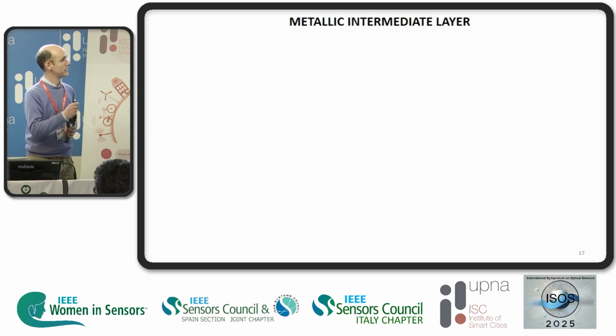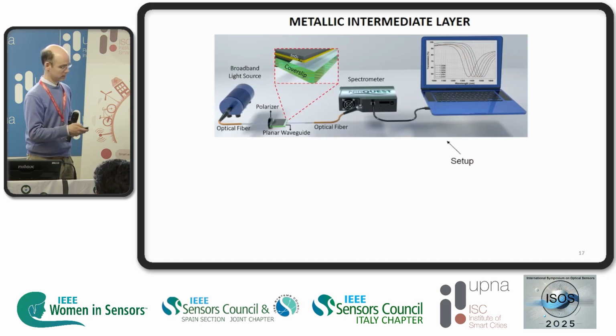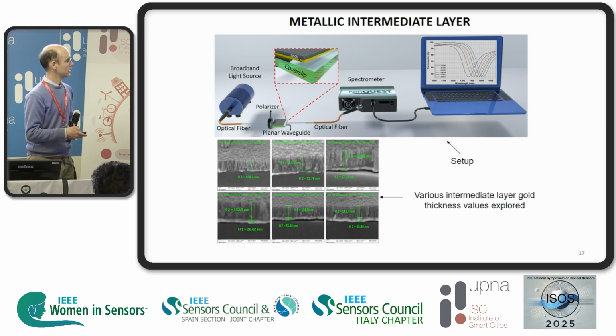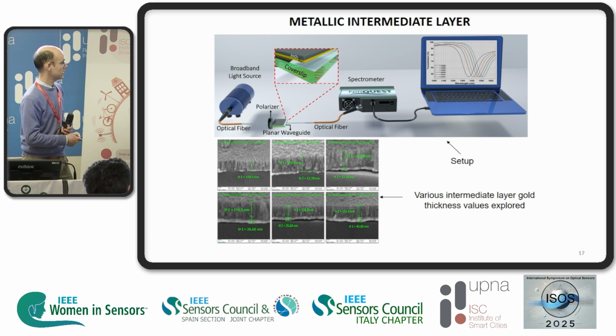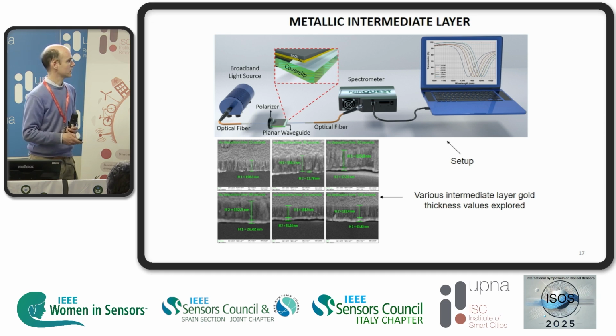We have deposited a dielectric with a metallic layer. This is the setup we have, and we have a cover slip. This is the waveguide, the thin film of tin dioxide, and we use gold for this example. We explore different gold thicknesses. So here, with just 15 seconds, we get a very narrow thickness of gold, which is nearly not visible. Here, 12 nanometers, 17, 26, 35, 45.